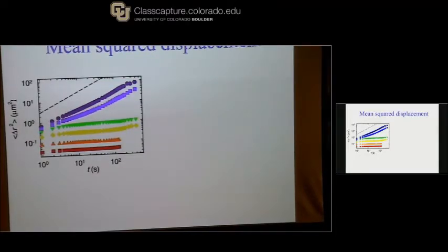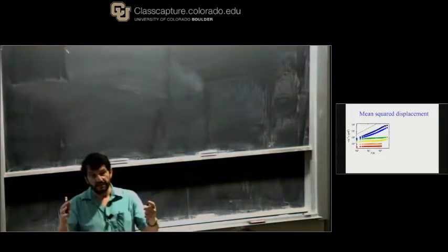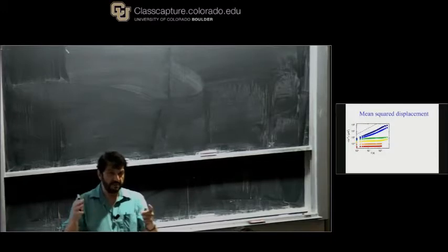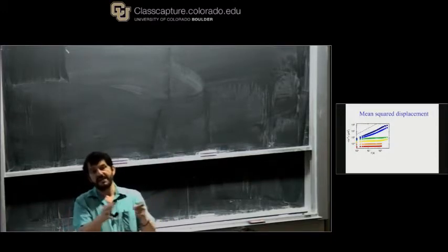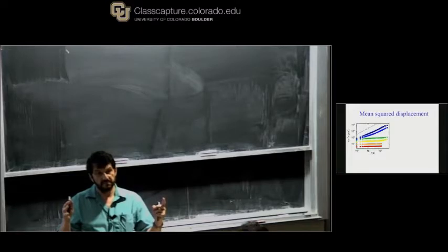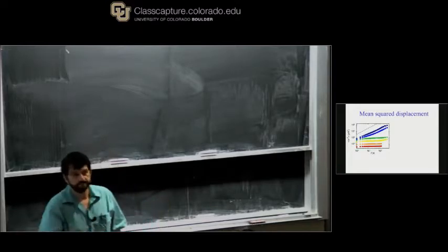You can calculate the, yes, sir? So is FCC in the bulk and BCC at the surface to the liquid? No, because we can only adjust the concentration or the volume fraction. And so if we go to high volume fractions, that's really strongly interacting, then it's FCC. If you go to low volume fractions, still a solid, it transitions between FCC and BCC. And if you go all the way to melting, it stays BCC and then eventually melts.